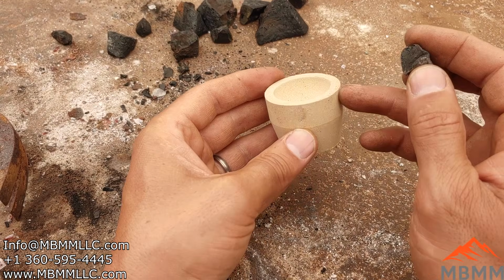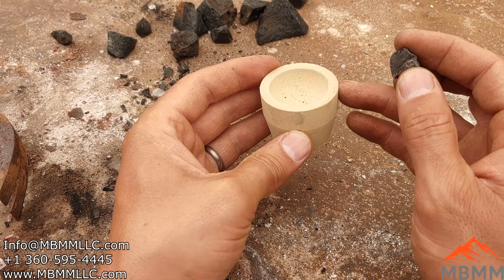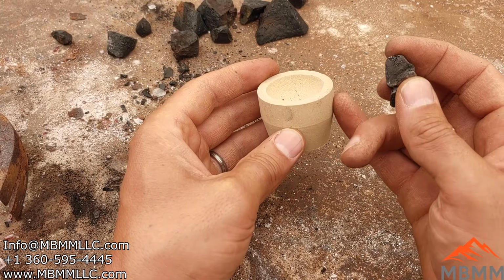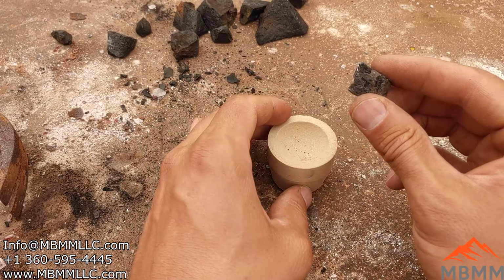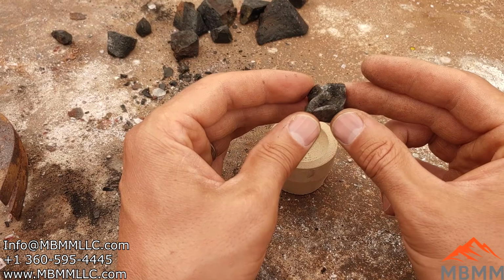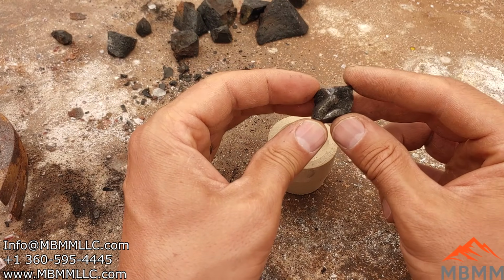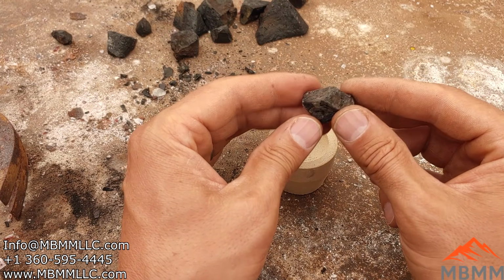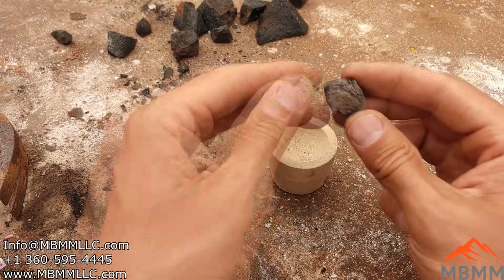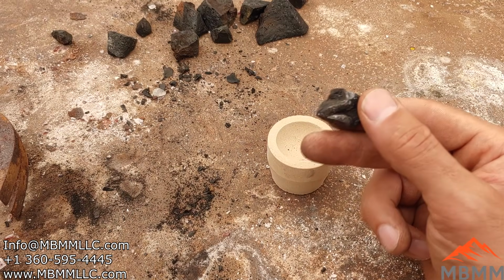So what I do is I put a cupel in the furnace and get it nice and warm and hot, to drive out all the moisture, and then I can put my lead block in there. So let's go put this in the furnace, and we'll let it start cupelling and oxidizing the lead away, and then hopefully we'll be left with some silver at the end.